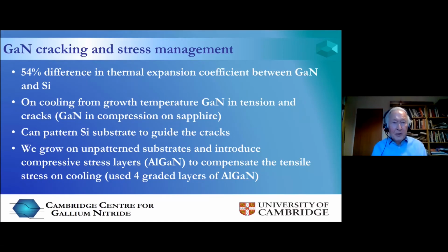And then the next problem to solve is this problem of cracking because of this 54% difference in thermal expansion coefficient between gallium nitride and silicon. And the LEDs which were being grown at the time on sapphire and silicon carbide, the differential thermal expansion coefficient works the other way. So gallium nitride is in compression on those substrates when you cool from the melt. But when you cool from the melt on the silicon, the gallium nitride is in tension, and so it cracks.